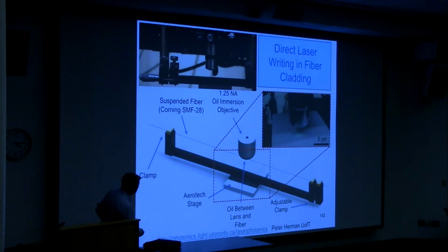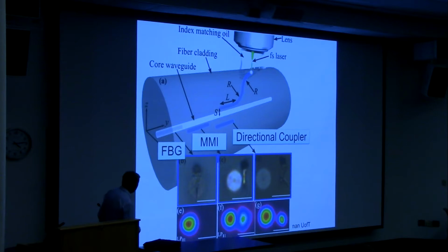So then there's a picture of the green frequency doubled femtosecond laser focusing through the fiber. You can see the shapes there. We use that to help align. What we can try to do is make laser-formed structures in the core, for example, to make fiber Bragg gratings. If we write them near the core, we can make it multi-mode and build well-known devices like multi-mode interferometers. Or if we go a little further away, it becomes a directional coupler.